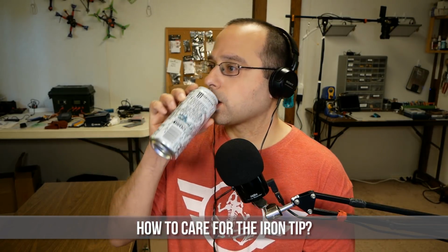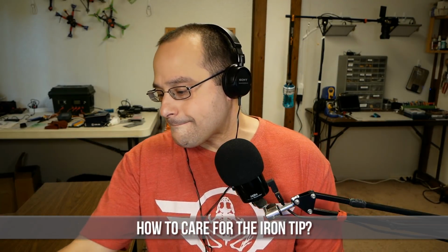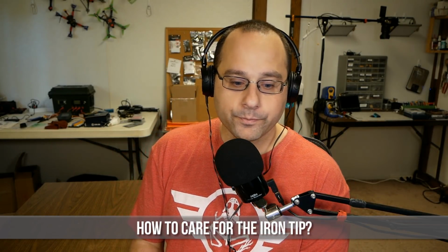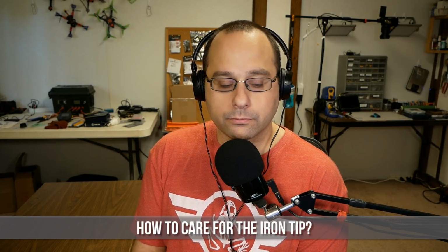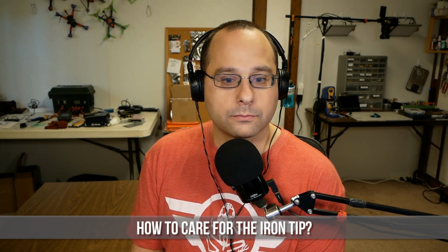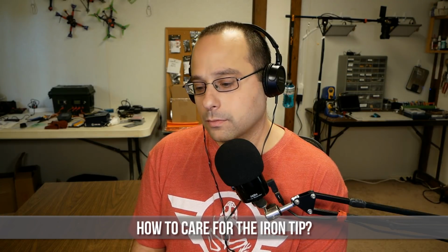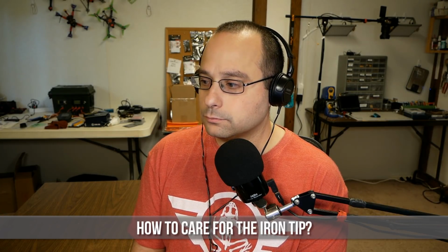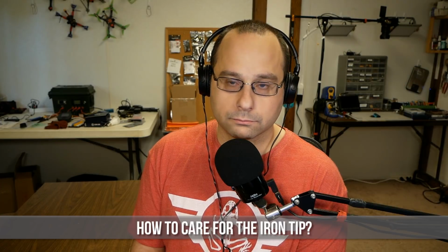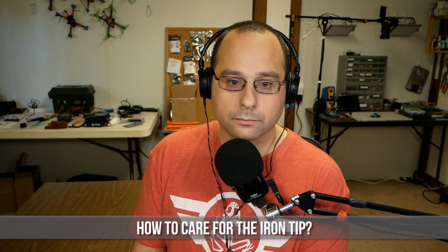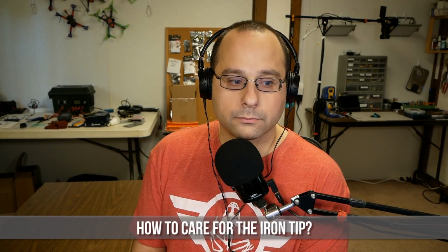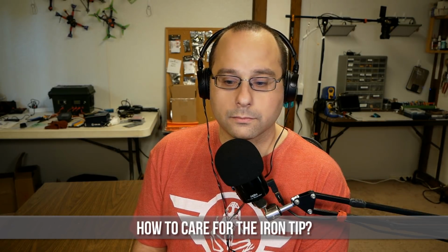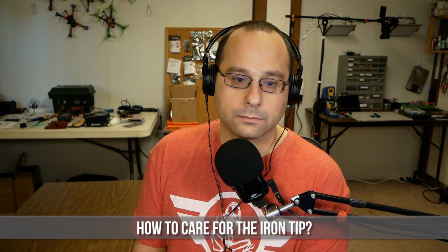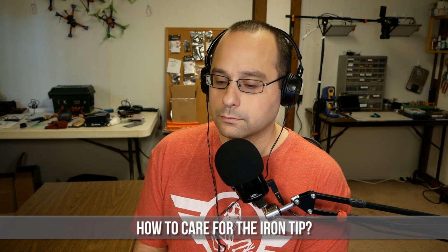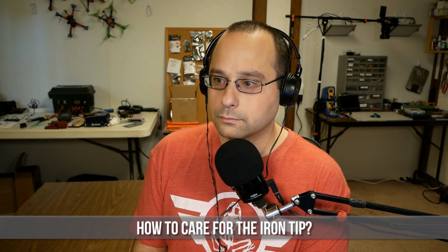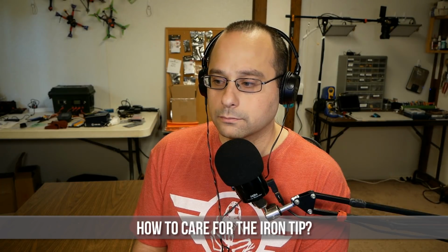When you're done soldering for the day, it is best to tin the iron with fresh solder. What that does is prevent oxidation and corrosion from the tip just sitting there. They have tip tinners on the market. You can just dip the iron into this little tin with a tip tinner, spin it, and it coats your tip, and then you can put it away for a week, a month, or whatever without losing any performance on your tip. So I'd recommend anyone do that, even when you first put a brand new tip on, tin it.